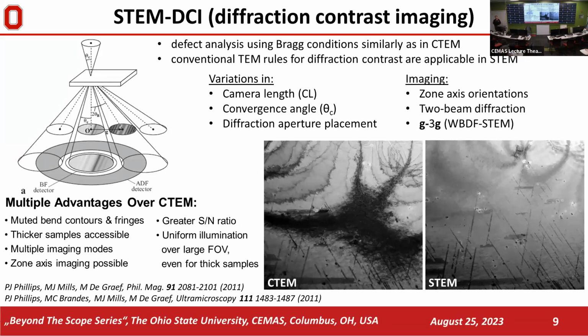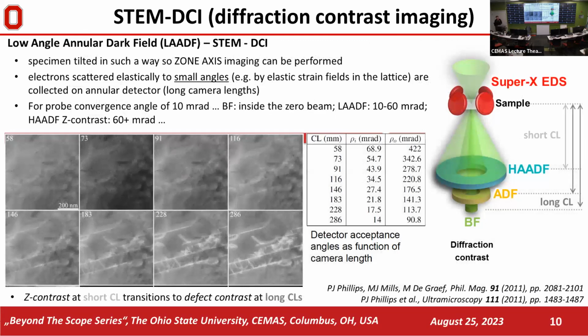We can do zone axis imaging, which is usually a starting point for us in our workflow, where we start with zone axis first, and then we tilt to two-beam conditions. We have a much greater signal-to-noise ratio, especially using now software tools such as the Thermo Fisher drift-corrected frame integration function, which can be applicable for all different STEM modes. We can obtain very nice signal-to-noise ratios in STEM. And last but not least, we have uniform illumination over a large field of view. So for thick samples, you usually can image basically the whole grain, and then you go to smaller landscapes. So a lot of benefits.